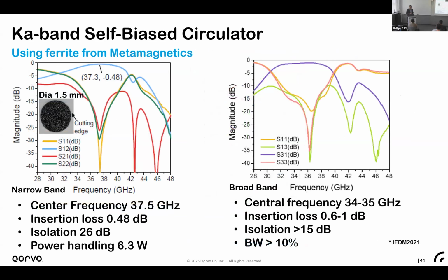And if you look at the Ka-band, the isolation is much better here. We were able to get like 26 dB, and the insertion loss is below 0.5 dB. This is largely because the material itself is more matured. And the power handling is also great. It can handle more than 6 watts of power. And by using different designs, you can have a narrow band and a broad band. I'm showing 2 cases here. On the left-hand side is a narrow band circulator, and on the right-hand side it covers like 10% bandwidth of the operating frequency. It's a broadband one.